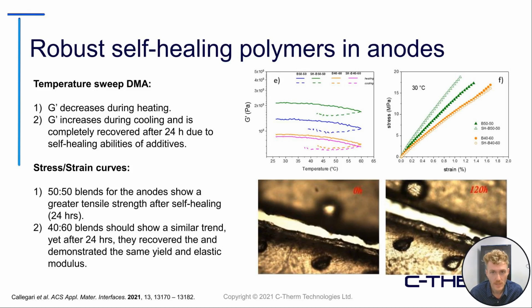By sweeping the temperature, they're able to see that these polymers in anodes behave very interestingly, where we have a decrease in G prime, or elastic modulus, upon heating, and then an increase back to the same level upon cooling, meaning that these are mechanically robust and thermomechanically stable as well.